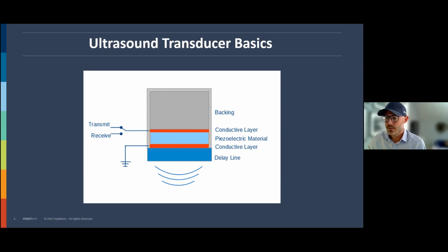So when the sound hits the part that you're inspecting, and then hits the back wall of it or a crack, it goes back through the delay line and into the piezoelectric material. And then again, the piezoelectric material starts to vibrate. And in the meantime, you will have the switch here turned from transmit to receive. And this vibration in the piezoelectric material creates a small, tiny charge on the top conductive layer. And this is what you use to make your signal that you're using to inspect.